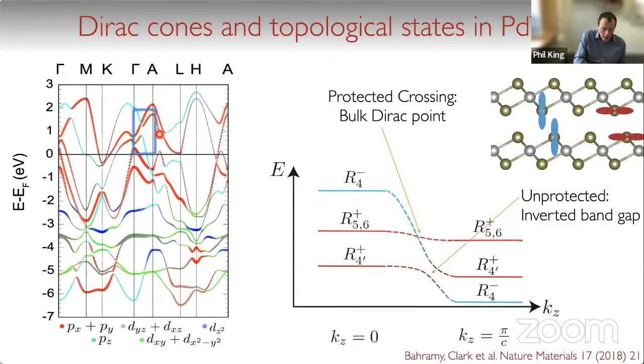And if we focus first above the Fermi level here, this is now again in our DFT calculations for palladium ditelluride, you see something rather similar to what I've just been talking about from our simple model. So you can see here the cyan coloring is the PZ-derived state, which is dispersing strongly downwards as a function of out-of-plane momentum here along the gamma ray direction of the Brillouin zone. And you have the red coloring here, which are the PX and the PY-derived states, which have a somewhat weaker dispersion. And these therefore cross over. And you can see exactly as we were discussing in the model, at the top crossing here, you have what seems to be a protected crossing where these bands really cross. And then just underneath that, you have a band gap that opens up.